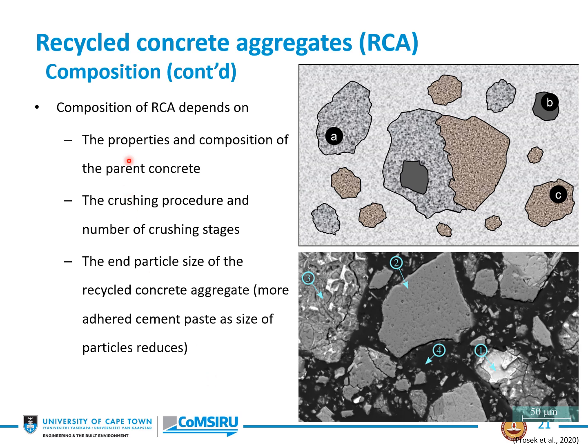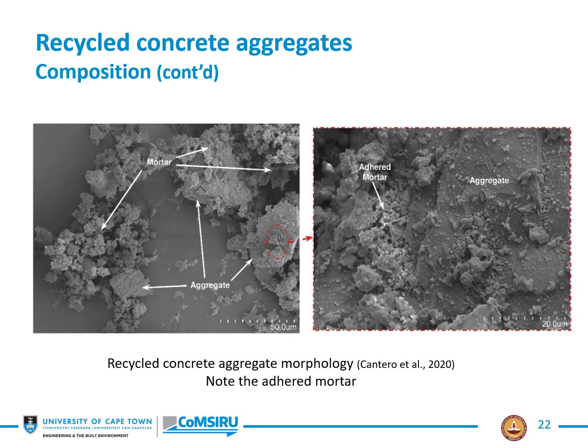So the composition then depends on the properties and composition of the parent concrete, the crushing procedures, and the number of crushing stages, and the end particle size of the recycled concrete aggregate. And here we see that as the particle size reduces, you get more of this adhered mortar. Here's a micrograph of the situation.